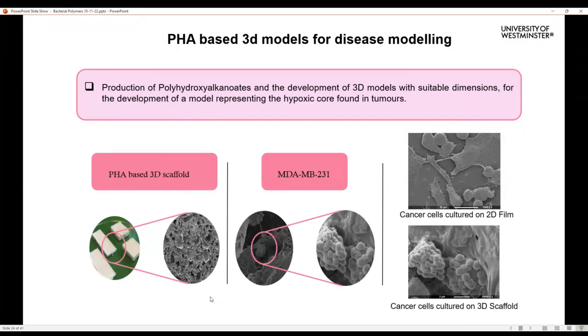Now we created some pores in this three-dimensional structure. And how did we do that? We mixed some porogen. In this case, we mixed some salt along with the polymer mix, poured that into the Teflon mold, and allowed it to dry. Once it was dry, we immersed those scaffolds in water to allow the salt to dissolve, and it dissolved away, leaving these pores behind. It's extremely important for these structures to have pores because it allows the cells to migrate, interact, and create that three-dimensional environment. So these are breast cancer cells. In the second image you can see this round circular mass of cells which looks like a bunch of grapes. These are basically breast cancer cells forming a tumor.